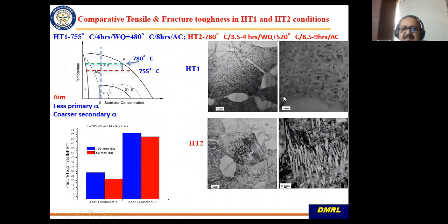Here the solution treatment was done lower, both solution treatment and aging, and the alpha precipitation was very fine, so it resulted in lower fracture toughness. But we changed the heat treatment, and when we get coarser alpha, we get higher fracture toughness also. So the same material can behave entirely differently. So you need to choose the heat treatment properly and microstructure properly to get the proper properties.